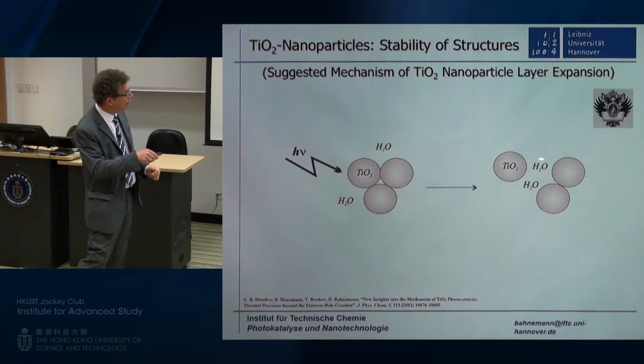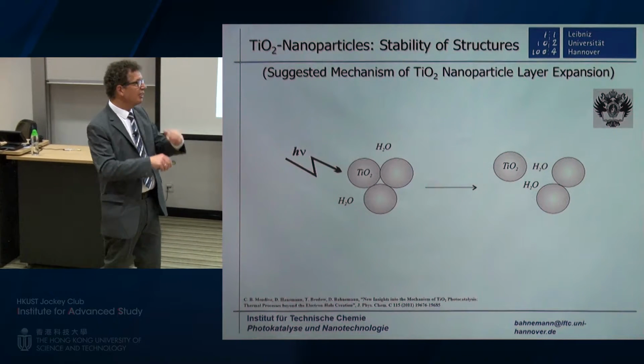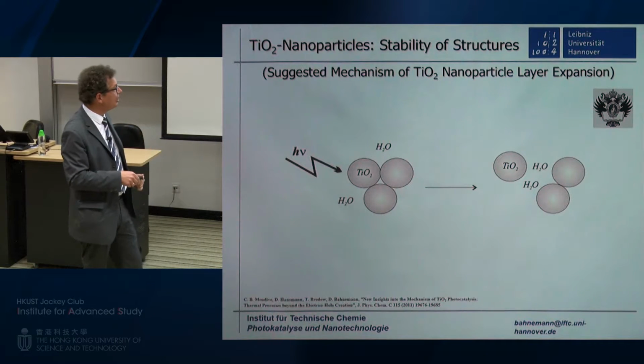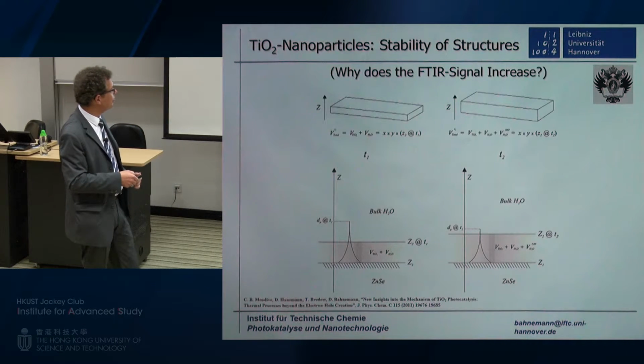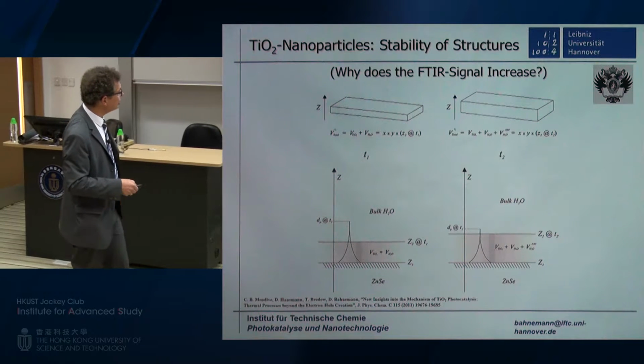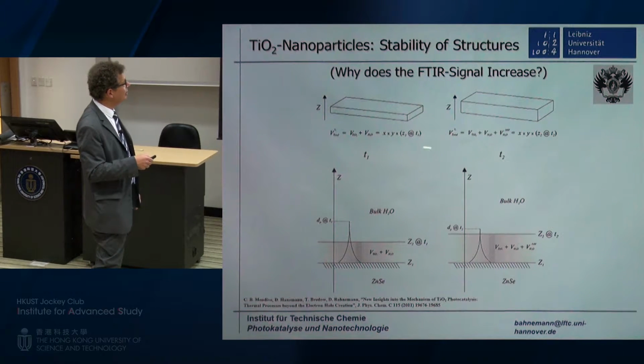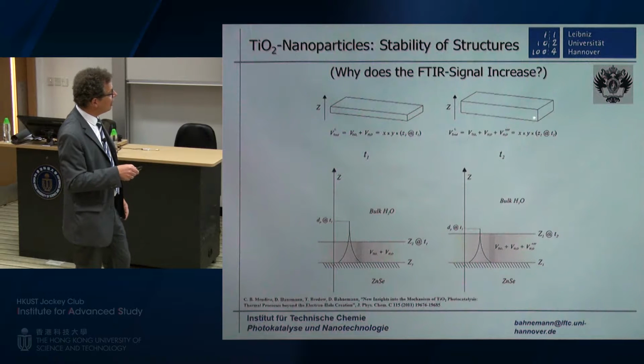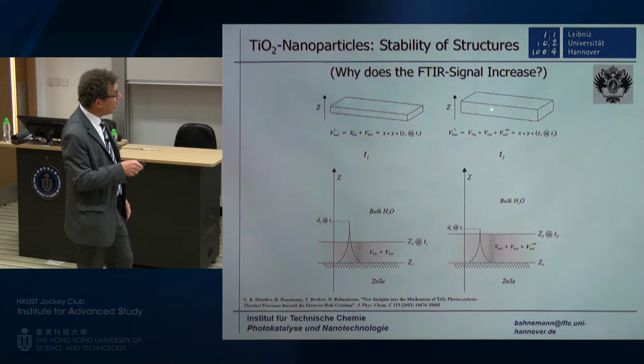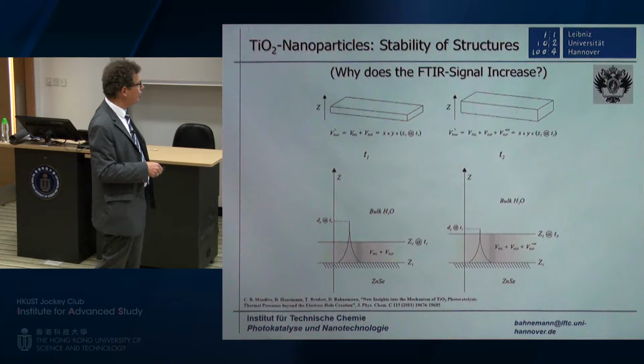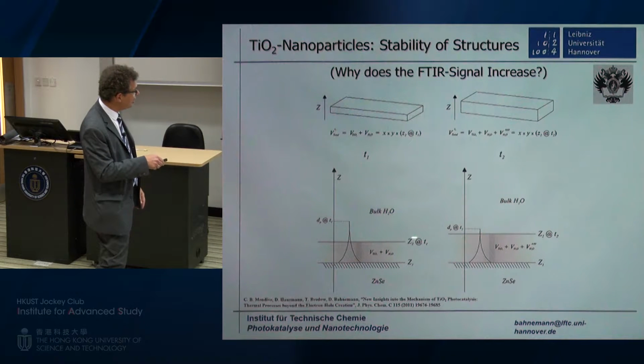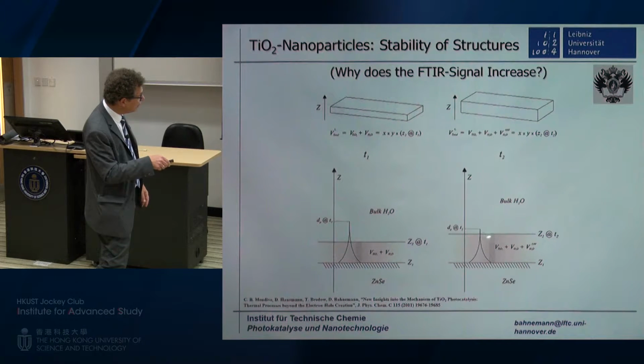But at the same time, if you intercalate more water into the system, you should get a little increase in the size of these systems. And we did some theoretical calculations of how much increase in the height we would expect when we have more water in the system. If you have a higher layer of TiO2, this means that your probing evanescent wave would see more of the TiO2 and less of the water.